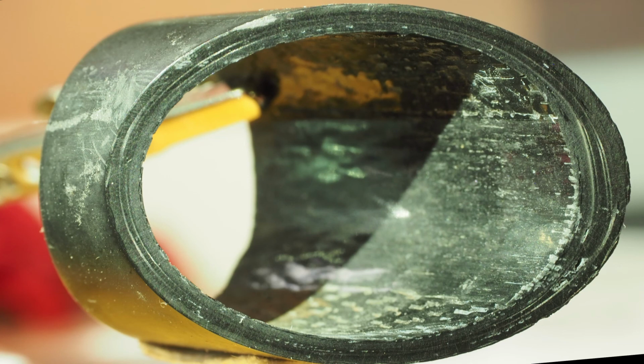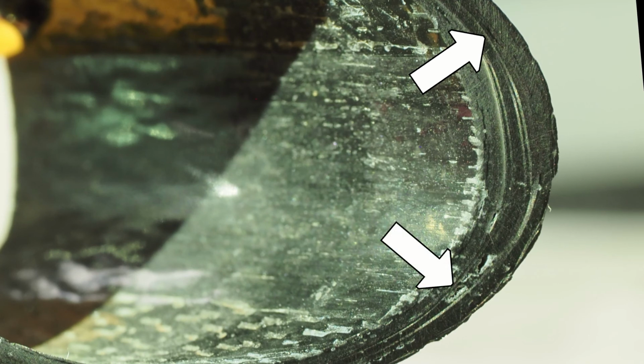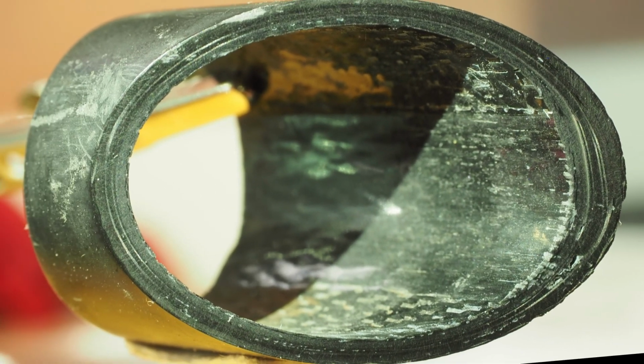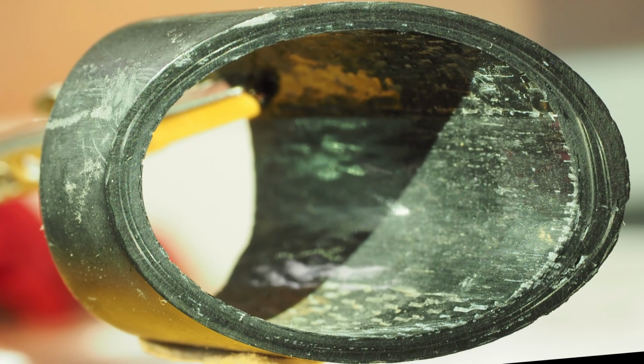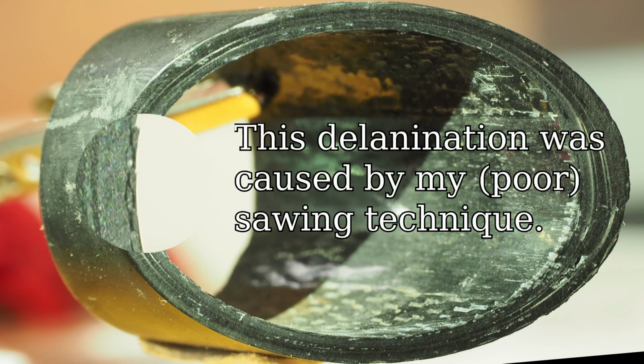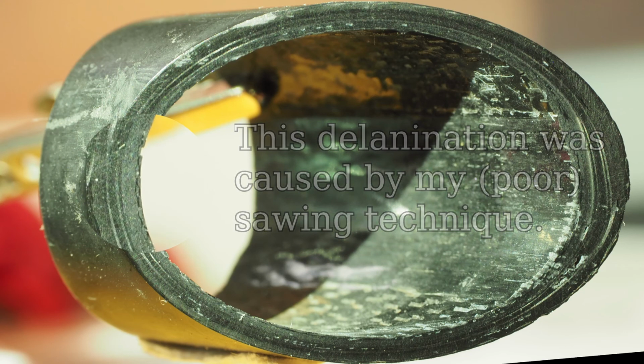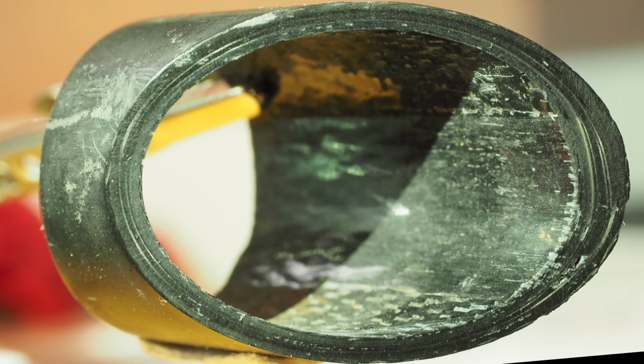Now for the not so good. I'm now pointing out a number of lack of bond defects and voids. Mostly these are quite small, but they are quite numerous. As the seat pin should not be subjected to any significant interlaminar shear loading, these defects should not be a problem. However, it is worrying that they are there. I may need to keep an eye on this seat pin, and indeed, I may just buy a replacement.